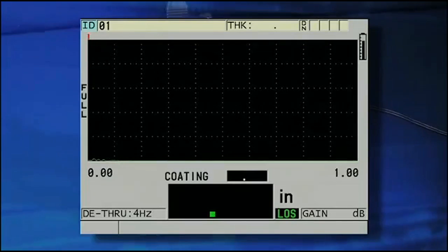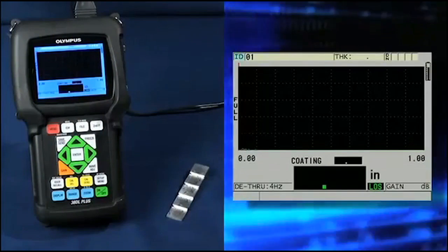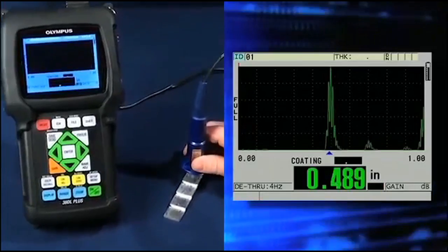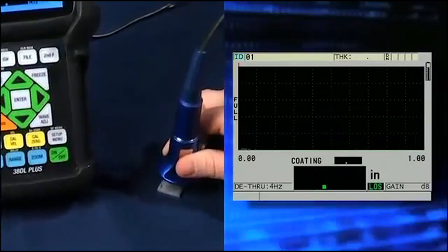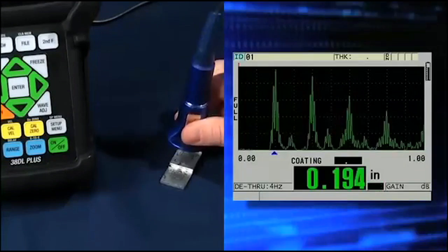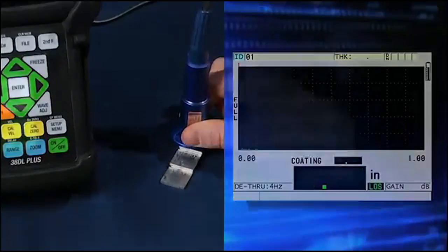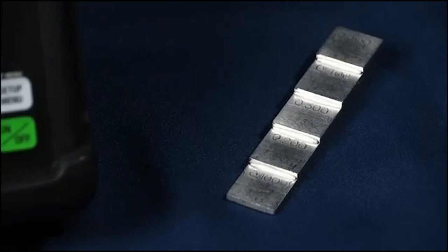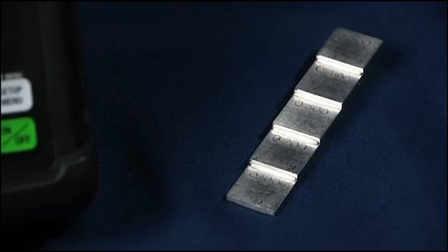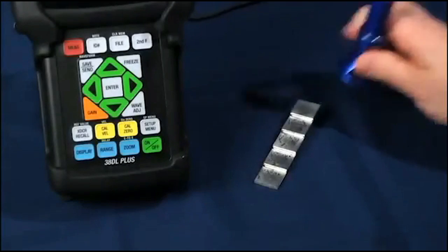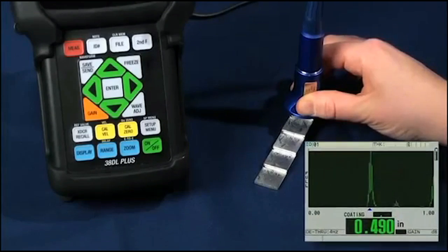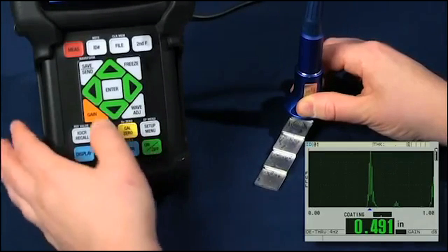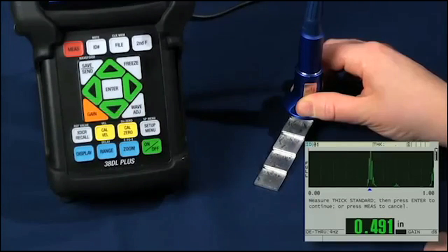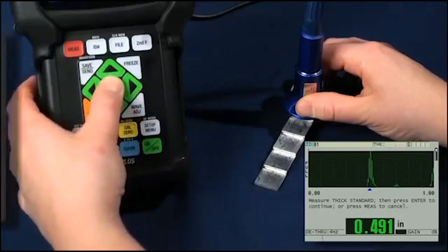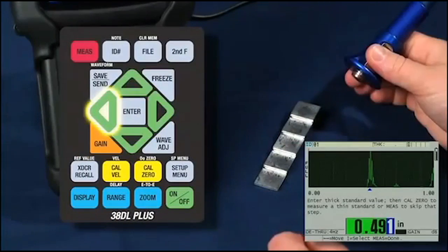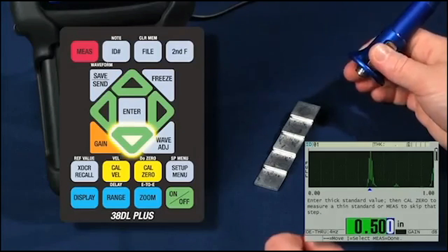At this point, we are now ready to calibrate the 38DL Plus in through-coat mode. In this example, we are going to be calibrating to a 5-step carbon steel test block, where the maximum thickness is 500 thousandths and the minimum thickness is 100 thousandths, with 100 thousandths steps in between. The test block does not have to have a coating on it in order to calibrate for the steel in through-coat mode. Simply couple to your thick standard, in this case the 500 thousandths, and press the Cal Vel key. Once we have a steady reading, press the enter key, and then use the right, left, up or down arrow keys to enter in the known thickness of the standard.